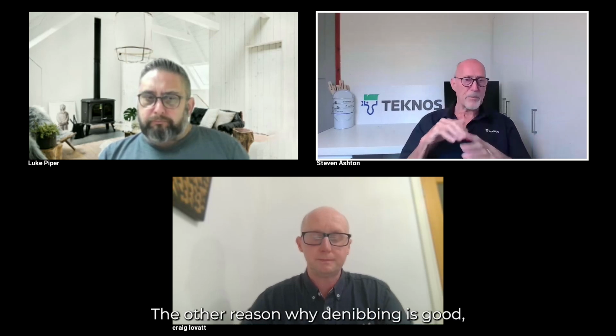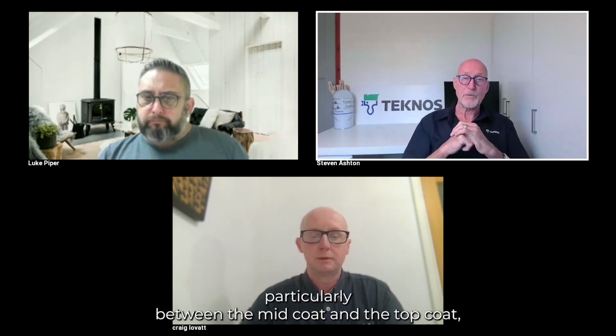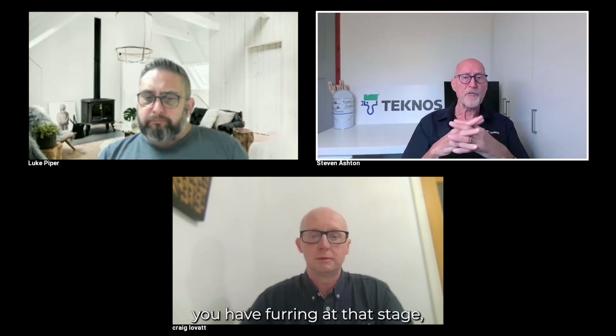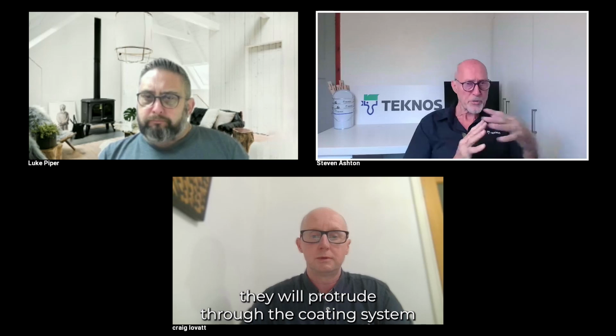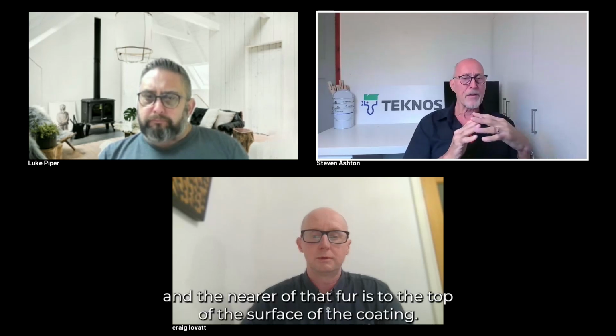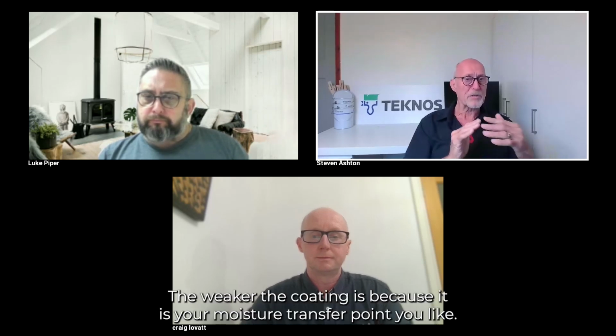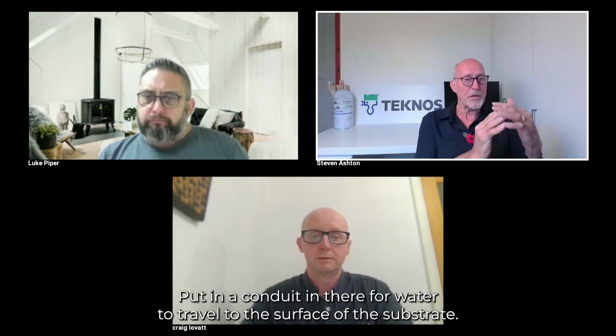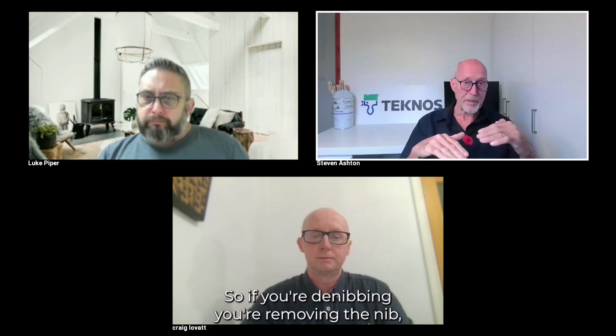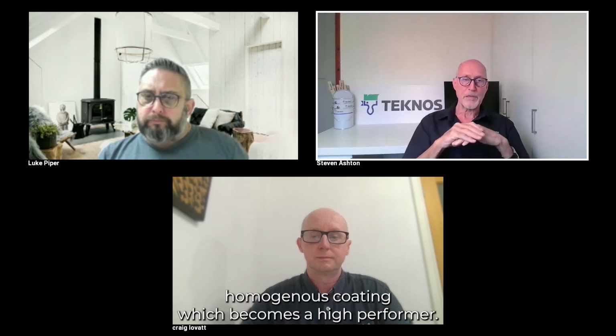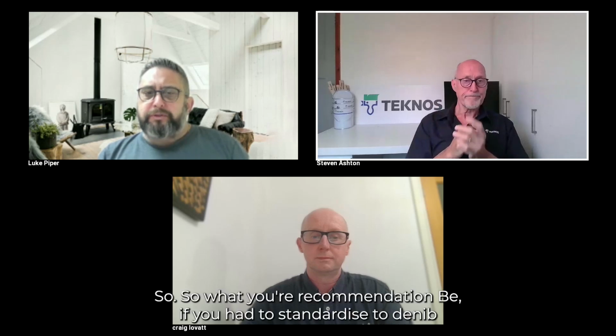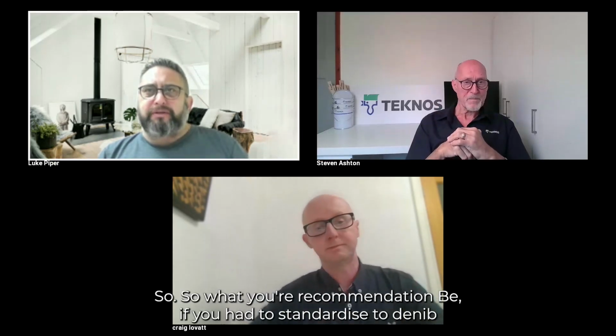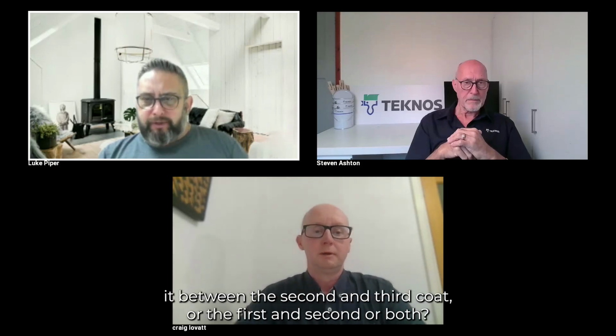The other reason why denibbing is good, particularly between the mid coat and the top coat, is because if you have furring at that stage, they will protrude through the coating system. And the nearer that fur is to the top of the surface of the coating, the weaker the coating is, because it is your moisture transfer point. It's like putting a conduit in there for water to travel to the surface of the substrate. So if you're denibbing, you're removing the nib, and therefore you've got a uniform homogeneous coating, which becomes a higher performer. So would your recommendation be, if you had to standardize, to denib between the second and third coat, or the first and second, or both?